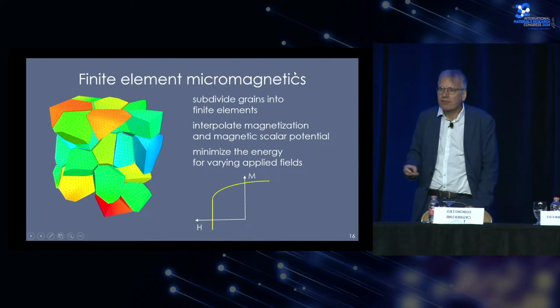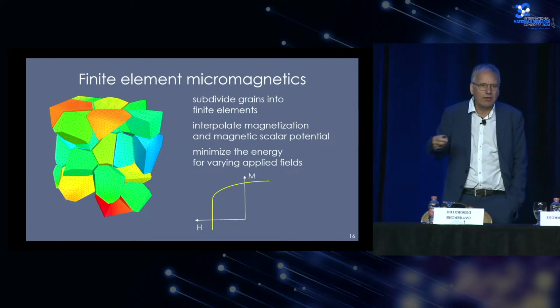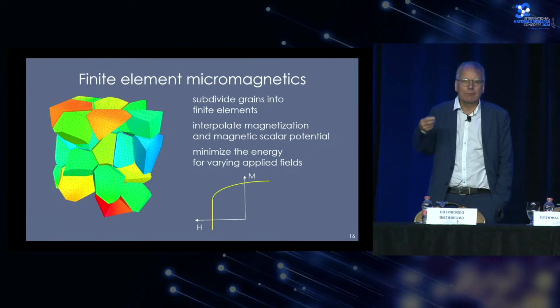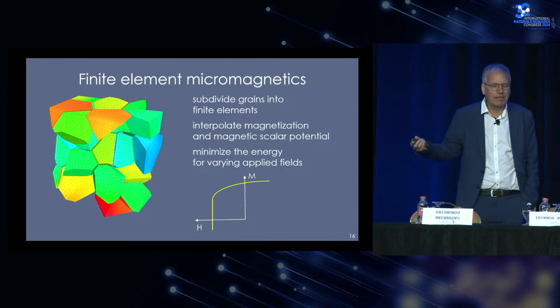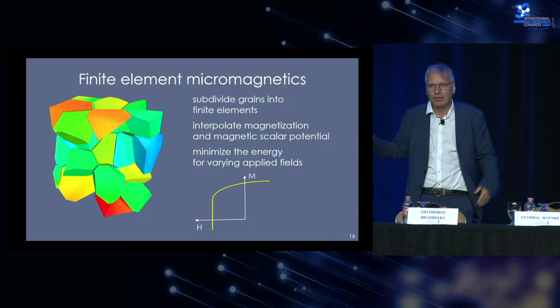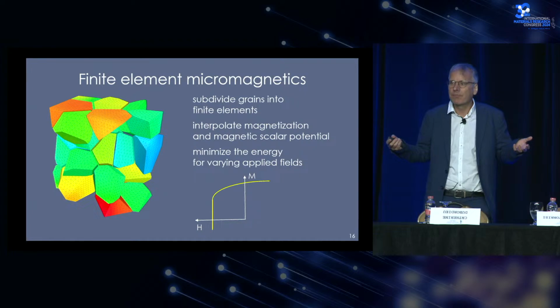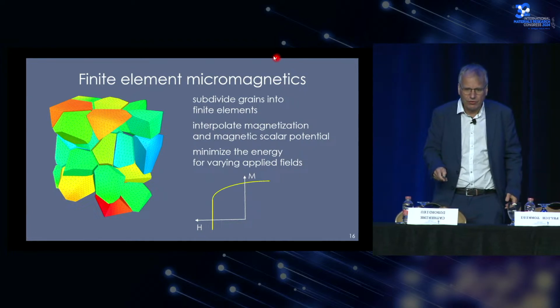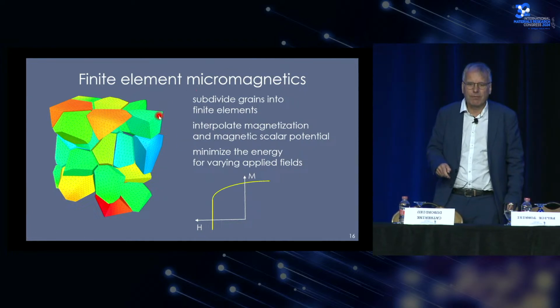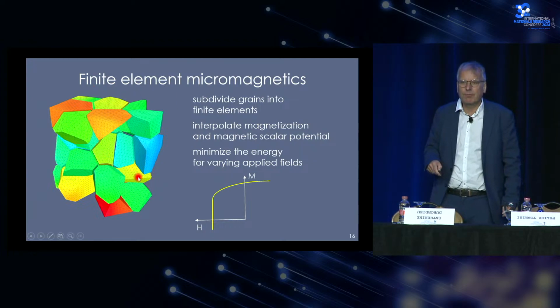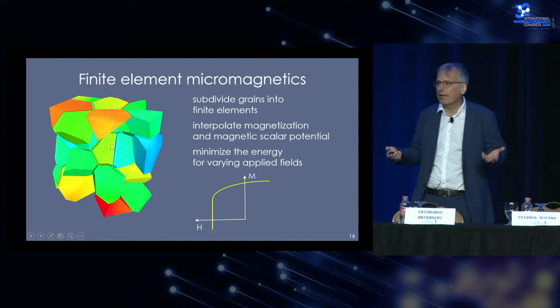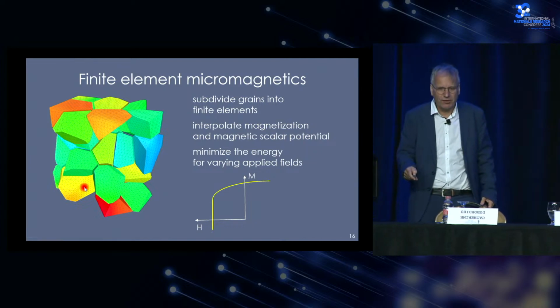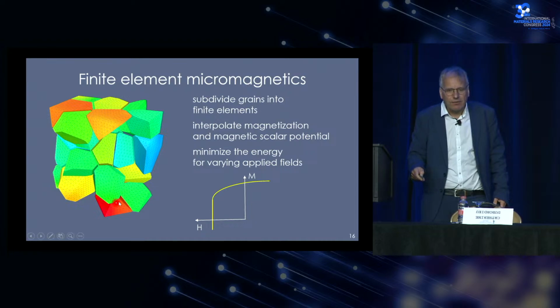What does this mean? So we do finite element simulation like we know from finite element simulation of structural mechanics or finite element simulation of electromagnetic devices. But we do this finite element simulation on the scale of the microstructure of the materials. So we create a synthetic microstructure, we create a finite element mesh of this synthetic microstructure, and we calculate these hysteresis loops that I have shown before.